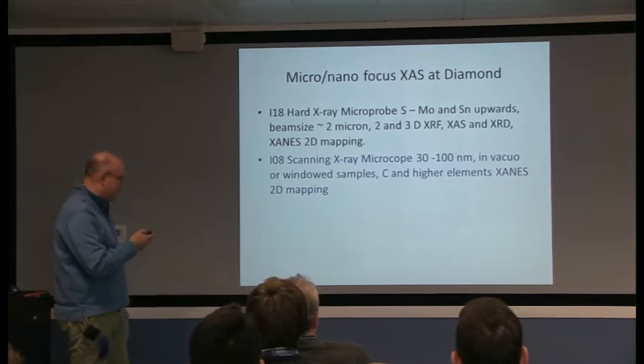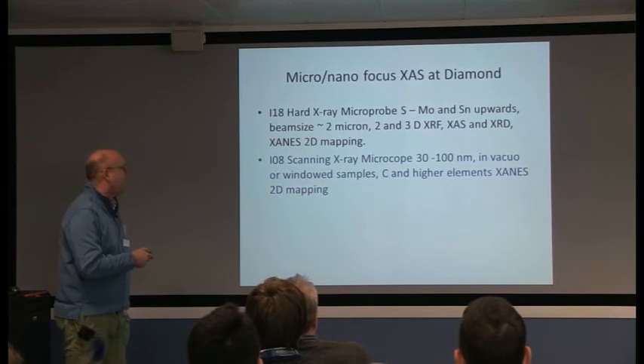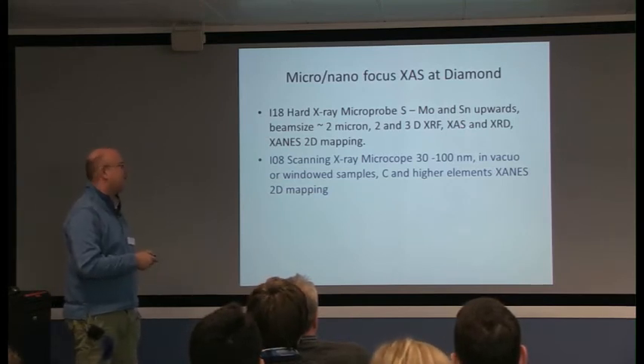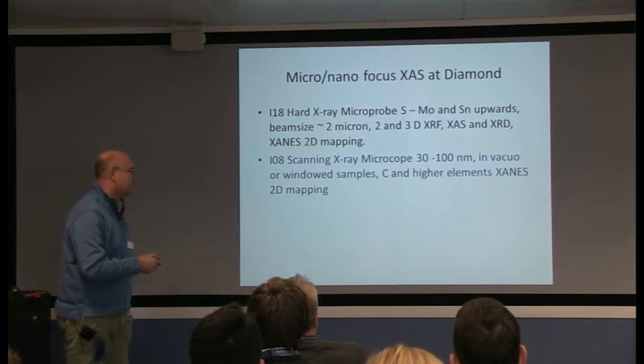We can get down to a beam size of around 2 microns. We can do 2 and 3 dimensional X-ray fluorescence, X-ray absorption spectroscopy, and also X-ray diffraction, so we can do X-ray diffraction tomography. We've just started doing that in the last, say, 9 months.